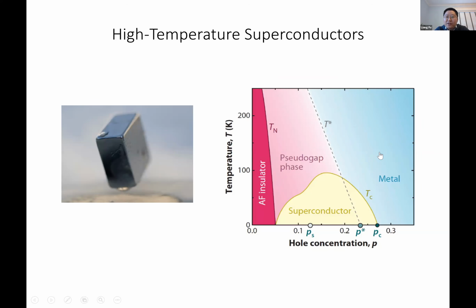Unlike an ordinary superconductor that comes out of a normal metal, in these cuprates the underlying state is an antiferromagnetic insulator, and upon doping, a superconducting state appears in a range of dopings with a maximum Tc. But there are other parts of this phase diagram that are equally interesting. The superconducting state seems to grow out of an unconventional state, a so-called pseudogap phase, et cetera. So this is a pretty simplified phase diagram of the cuprates, and it has long been a mystery to understand.